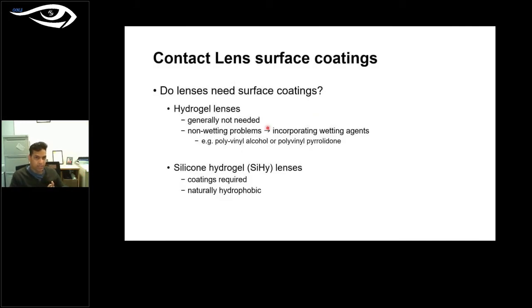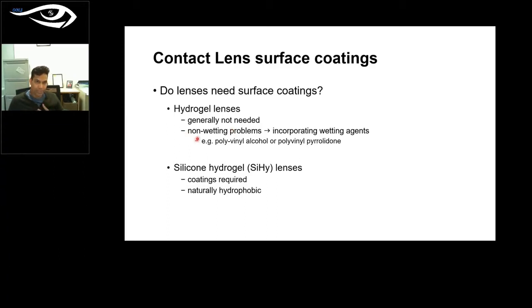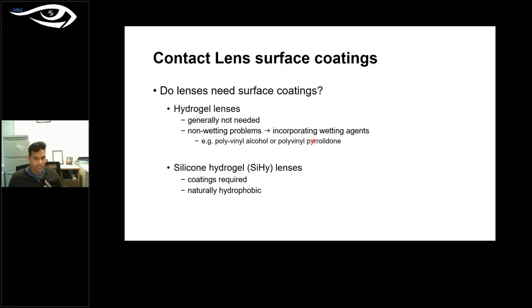Okay, so the first question to be asked is, do lenses need surface coatings or surface modifications? Hydrogel lenses generally do not need surface modifications or surface coatings, because if there are any non-wetting problems associated with hydrogel lenses, we generally incorporate more wetting agents. So when I say wetting agents, you have a bulk polymer, and then we tend to add extra copolymers or monomers into the matrix so that we make the lens more comfortable. A few examples of wetting agents are polyvinyl alcohol or polyvinyl pyrrolidone, which we can use to enhance wetting properties of the hydrogel lenses.